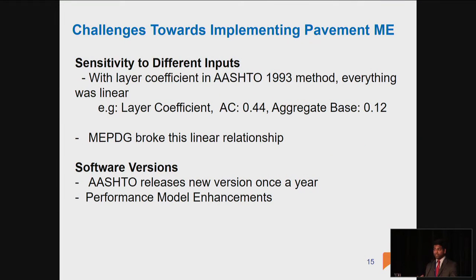AASHTO 93 empirical design was easy. You only use a layer coefficient. For Virginia, we use a layer coefficient of 0.44 for asphalt, and for the aggregate base, it's 0.12. So that means 4 inches of aggregate base is equivalent to 1 inch of asphalt. MEPDG doesn't have this linear relationship, so it changed everything. I'm going to discuss in the next few slides what issues we are seeing.